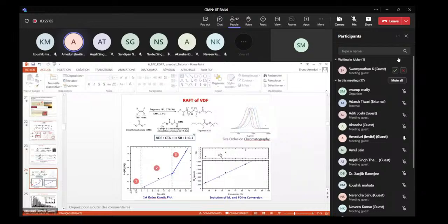And you see here that you have an increase of the dispersity. Of course, we are below 1.4, but this increase, which is detrimental to a real control, is because, as I mentioned before, there is this head-to-head addition which gives the CH2 xanthate.